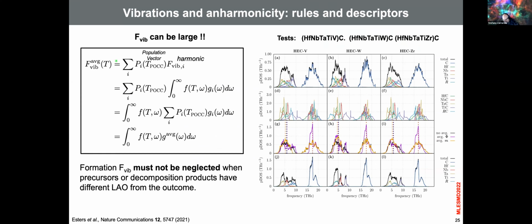Okay, because disorder is really P1. But actually, we did with our POCC systems. Look at here. For every one of these small configurations, we get the harmonic vibrations, all right? The harmonic free energy, the harmonic density of states, the harmonic everything, right? And then we make the convolution here. We make the convolution, and we get the disorder free energy. Okay, so you get the disorder density of states of a vibration, etc.